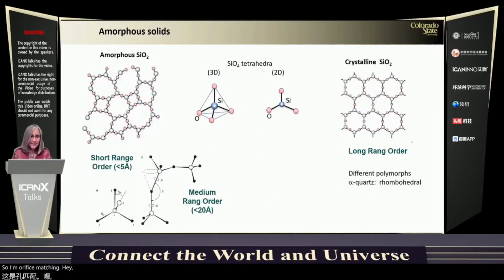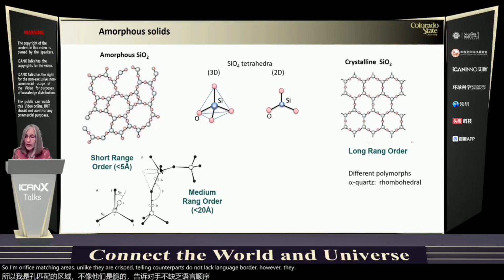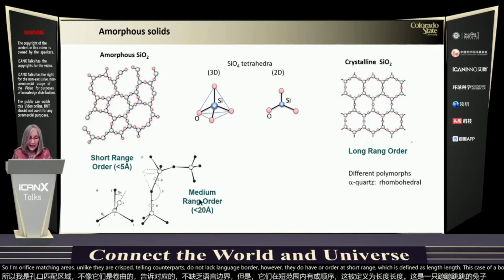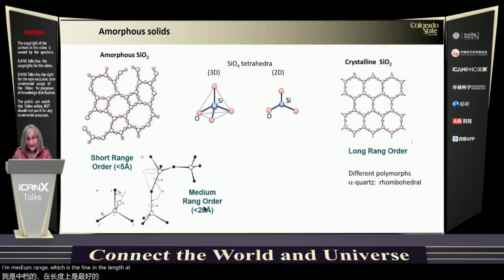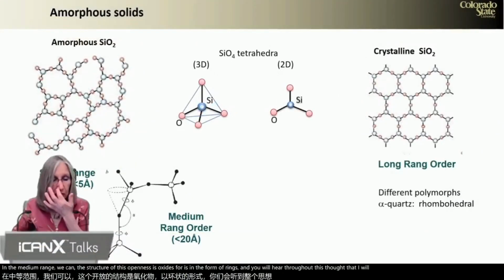So amorphous materials, unlike their crystalline counterparts, lack long-range order. However, they do have order at short range, which is defined as length scales of about 5 angstroms, and medium range, which is defined in the length scales of about 20 angstroms. So in the short range, amorphous oxides, and I show the case here of silicon dioxide, are arranged in the form of polyhedra. This is a tetrahedron in the case of silicon dioxide, in which silicon is mainly covalently bound to oxygen. In the medium range, the structure of these oxides is in the form of rings. And you will hear throughout this talk that I will refer to this ring formation.